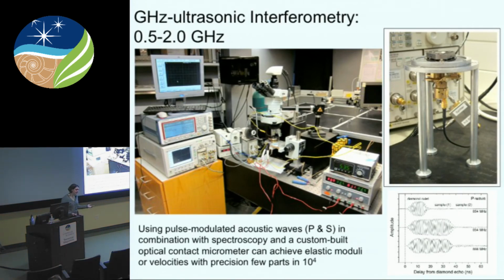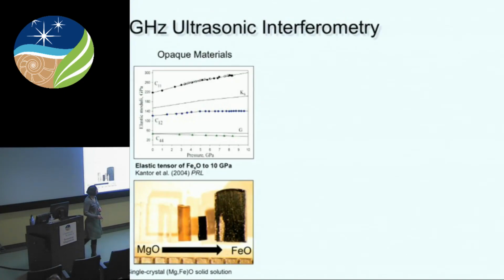So part of my NSF postdoc is working with Steve Jacobson at Northwestern because he uniquely has the ability to do gigahertz frequency ultrasonic interferometry. And so what I've proposed to do is develop the high temperature capabilities, and that's what's shown here. We're actually doing an experiment at 535 degrees C in the diamond cell. And we've moved it. This is where I overtook every instrument in Steve's lab. And it turns out his grad students don't like it when I do that. So this is a big part of the development, to be able to push to higher temperatures.